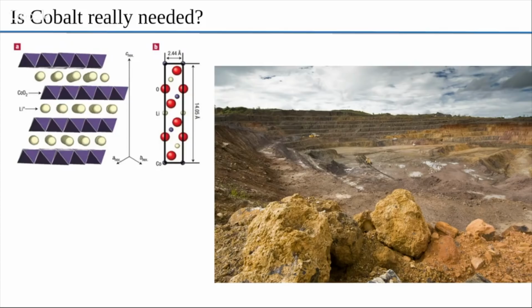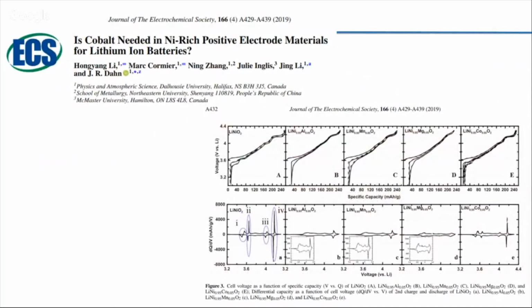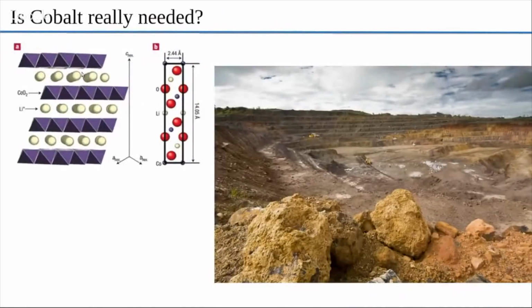And recently, there was a really interesting article by Professor Jeff Dahn. Their group did a very systematic study into different alternative chemistries, and they wondered if they can really replace cobalt. And the summary of this research is cobalt is really not needed. They thought cobalt is needed because the initial understanding of the battery community was that if you take away all the cobalt from the middle of these structures, the scaffolding, the structure will collapse and you may compromise the power density of the battery. So they were able to compensate for the cobalt using aluminum. So that's how the NCA came into existence. They were able to compensate the power density by bringing in aluminum and nickel to a certain extent.